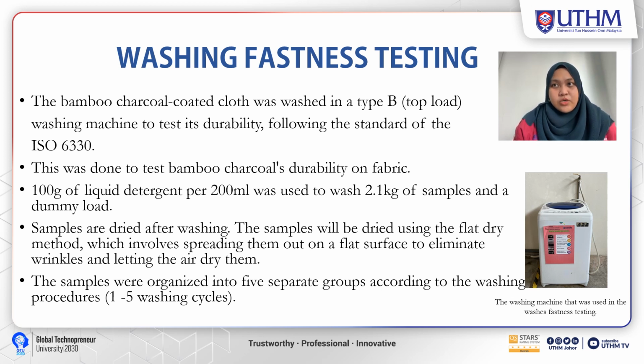100 grams of liquid detergent per 200ml was used to wash 2.1kg of samples and a dummy load. Samples are dried after washing. The samples were dried using the flat dry method, which involves spreading them out on a flat surface to eliminate wrinkles and letting the air dry them. The samples were organized into 5 separate groups according to the washing procedures, from 1 to 5 washing cycles.